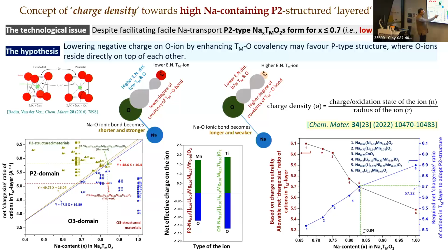All we did here is replace, either have manganese 4+ or titanium 4+, same amount with everything else remaining the same. And indeed, we saw that this having a lower charge to size ratio crystallized in O3 structure, this having a higher charge to size ratio crystallized in the P2 structure under exactly the same condition. And again, DFT showed that, as expected, this had a greater effective negative charge on the oxygen ion, so it would not like to adapt this coordination, it adapted this coordination, and the other way around for this.